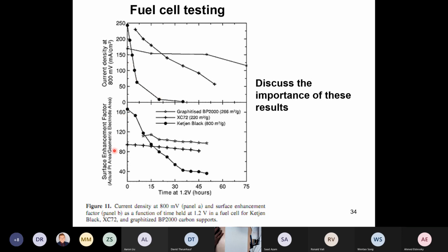And at the same time, they're measuring what's called the surface enhancement factor. This is the surface area of the electrochemically active platinum compared to the geometric electrode area. So if you have a centimeter squared of electrode, you would start with 160 centimeters squared of platinum electrochemically active surface area per centimeter squared of electrode. And then you can see what happens, that just drops. This is because of the carbon burn-off, where you're losing electric connection to these platinum particles. And this current density at 800 millivolts just tanks.